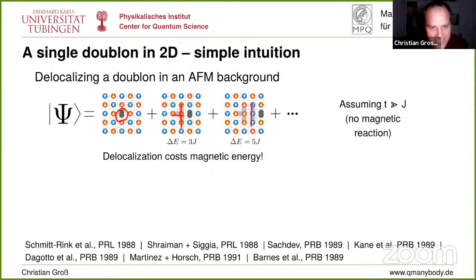And it turns out that you cannot find any combination of whatever spins that lets this doublon actually move away. What I assume in this picture is, of course, that the t timescale is much faster than the J timescale, because the spin can also heal, by reacting dynamically, which I completely neglect in this cartoon.